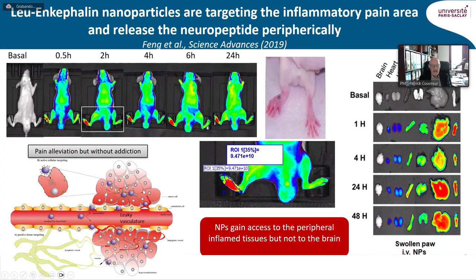And you can see that after intravenous administration, over time, there was a concentration, a targeting of those nanoparticles at the level of the right painful inflammatory paw. You have a magnification here, and there was no access for those nanoparticles to the left healthy paw, which was used as a control.